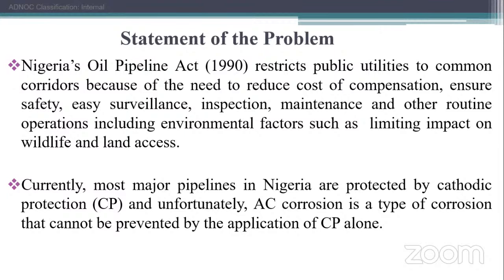So that's why we introduce cathodic protection. Cathodic protection is like trying to protect that pipeline at those small holes that the coating has missed, those defects that we find in the coating. The cathodic protection is meant to protect the pipeline at those points. But unfortunately, AC corrosion is unique, unlike the other forms of corrosion that I've told you about.